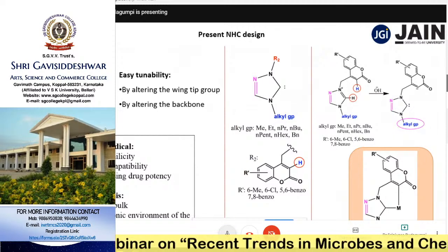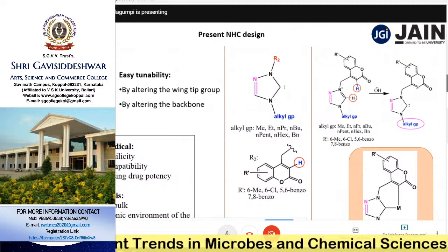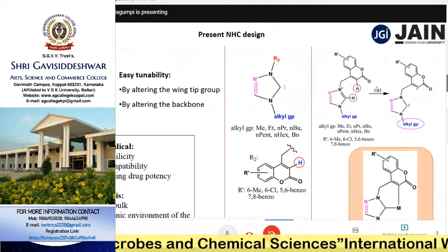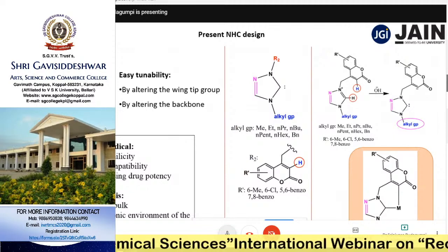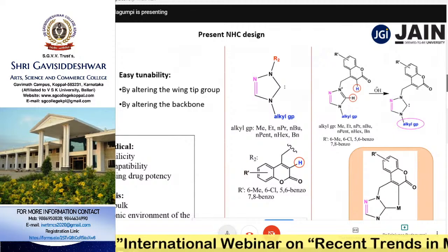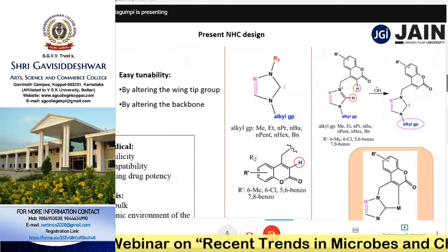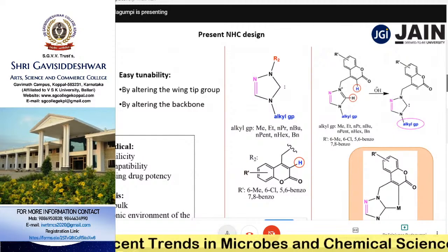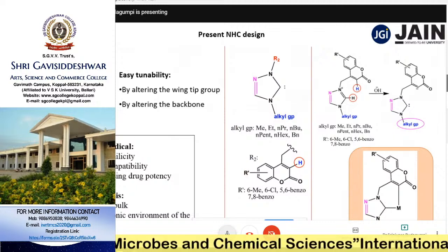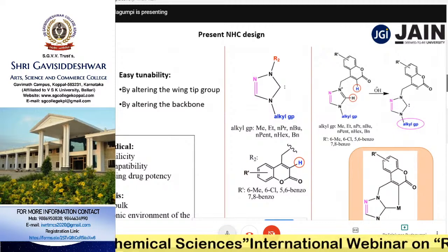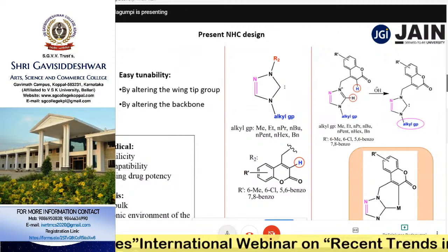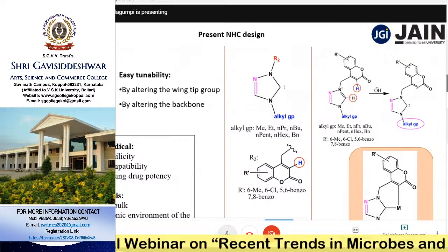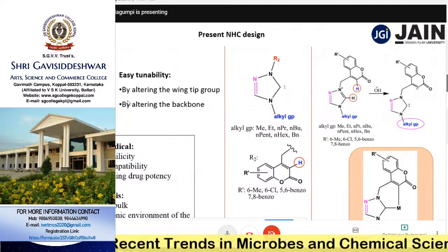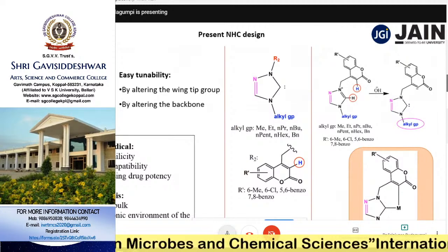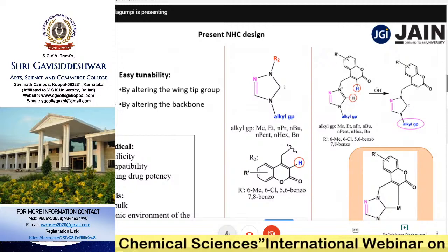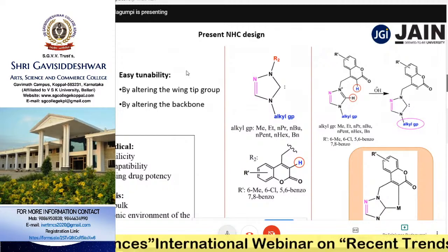Fine. The second objective of using N-heterocyclic carbenes is the possibility of altering the backbone substitutions here. This is called the C4 and C5 carbon atom. So there is a chance that you can alter the electron donating or electron withdrawing groups here at the backbone of the azole ring, which can indirectly affect the donor strength of the NHC. Through this you can control the steric or electronic requirements around the resulting complex, which is indeed effective for catalytic applications.